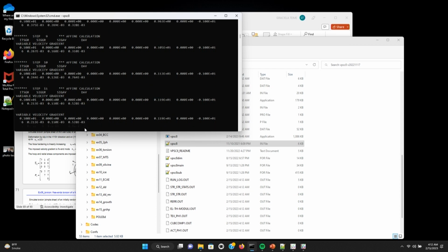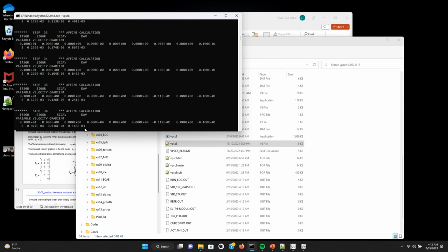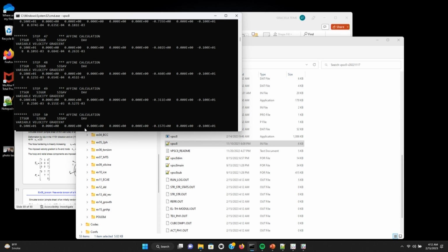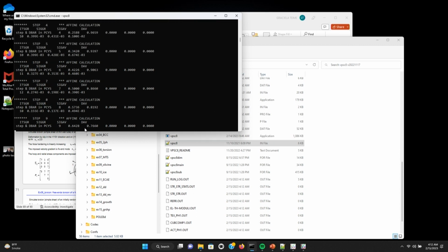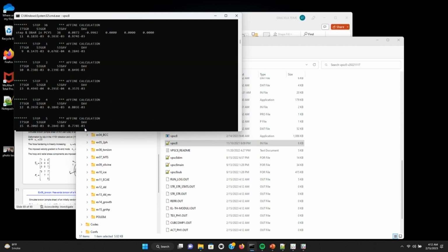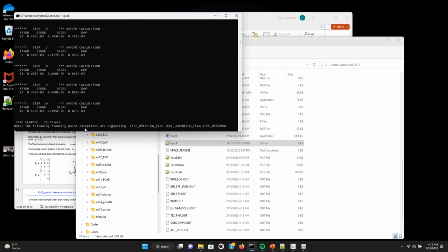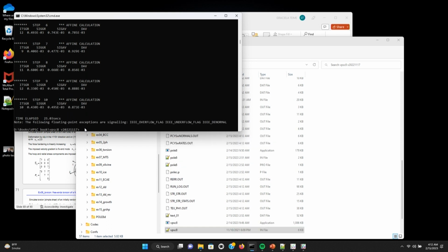So now this is performing the first 50 steps of the deformation with the non-homogeneous velocity gradient. Then the yield surface, 32 probes of the yield surface. Of course, when you probe the yield surface, there is no hardening. You don't update the hardening. You just probe but don't update the hardening. And then 10 steps for the Lankford coefficient.